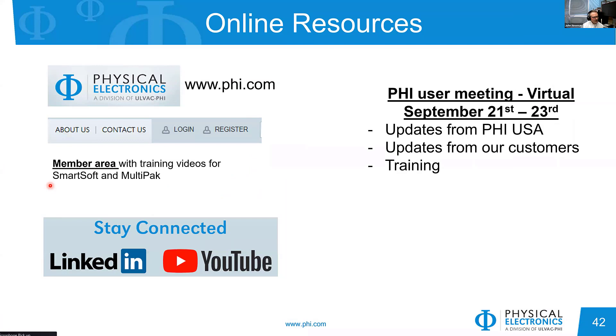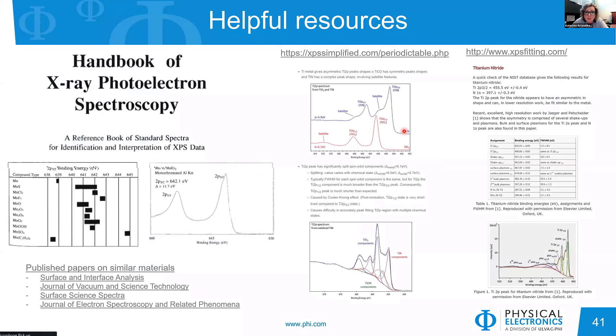Question: how much do spin-orbit splitting values — for example, the energy gap and area ratio — vary in XPS peaks in real samples? As shown in the titanium 2p example, the metal has a splitting of 6.1 eV, the nitride 6.0, and the oxide 5.7. There is enough variability that fitting won't work well if you use 6.1 for all of them — it's very compound-dependent. That's why, if you don't use the information already available from references, you may think something is wrong, but there may be variability you're not taking into account.